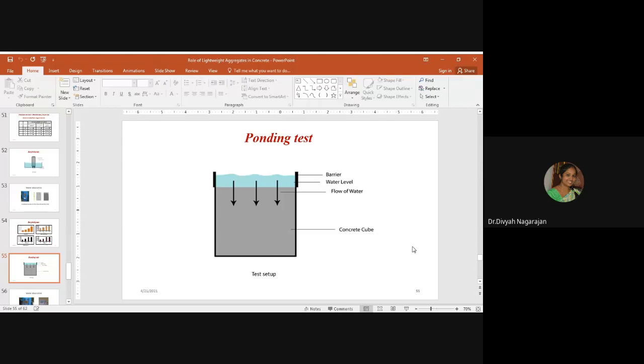Ponding test. The ponding test is carried out in order to find out the penetration of water towards gravity, as in the real case that occurs when there is stagnation of rainwater or stagnation of water on concrete structures. So above a concrete cube, a barrier is built, and the water level is maintained for about 24 hours, and the flow of water occurs towards gravity. And this is the test setup.